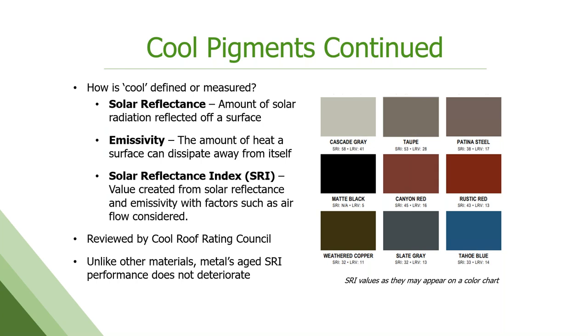That three-year aged value, right? You want it to start cool, but you want it to stay cool too. You don't want that property to drop off. And that is one huge advantage that coated metal has. Because these paints have such great longevity and they don't change color or properties over time, these initial cool properties stay for a very, very long time, as opposed to asphalt roofing and some field applied coatings, whose SRI values tend to drop off significantly in that 3 to 5 year range, while metal does not.